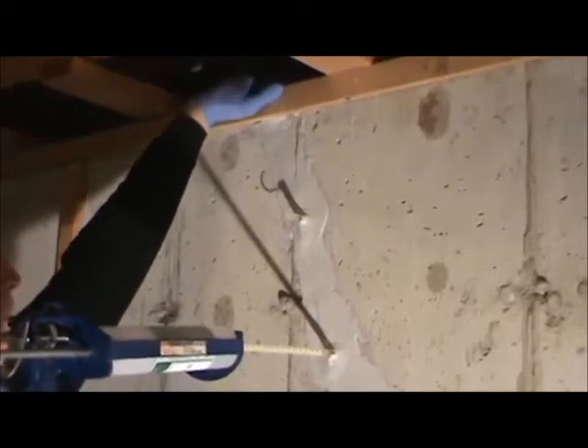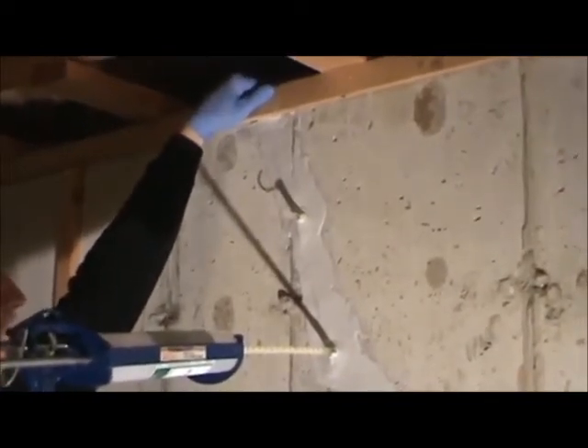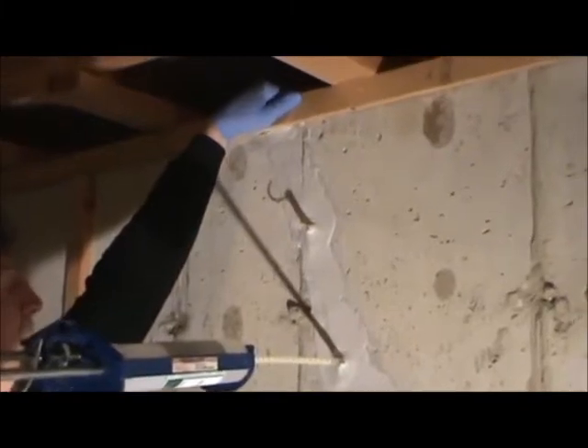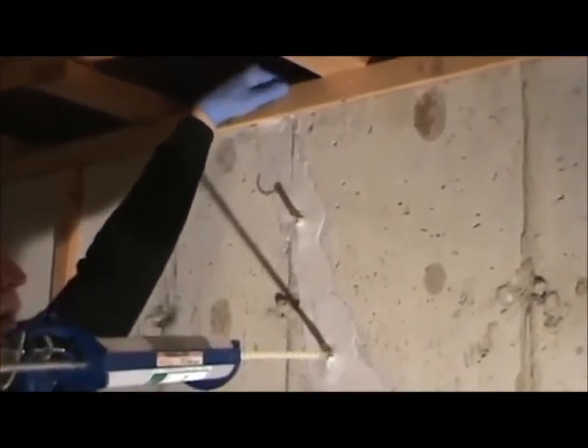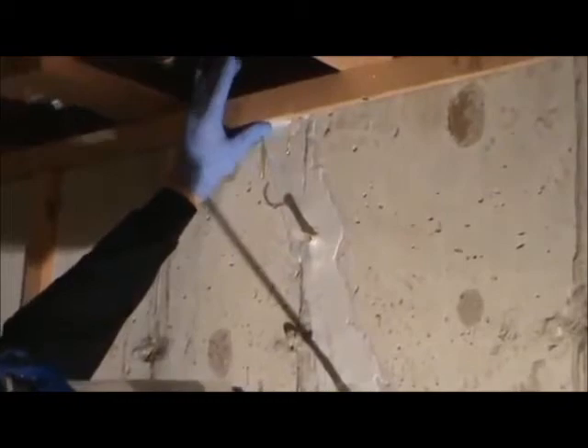Earlier, we mentioned leaving the top 1/8 inch of the crack unsealed. This is done so that you can see when you've filled the crack. If you surface seal to the very top of the crack, resin will flow over the top of the band board and generally cause a mess. After you've filled the crack, check each port for resin and top off any ports that need it.